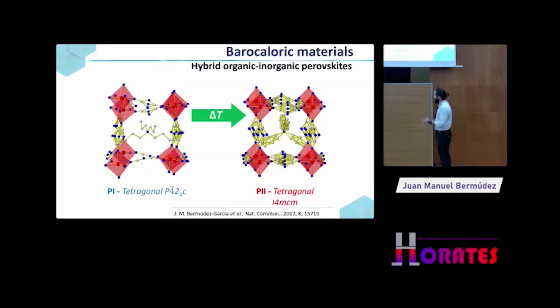And even more, we studied the effects of pressure on those materials, and we observed that we were able to induce this phase transition by starting in this specific phase and applying pressure. We could go towards this phase, and then under depressurization, we can go back to this state. So we could drive the transition upon temperature and also by applying pressure. So that specific material fulfilled the main requirements to be a promising barocaloric material.